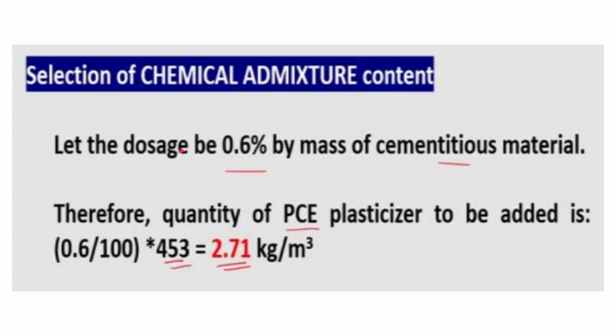Now selection of chemical admixture. Let us assume that the dosage of chemical admixture is 0.6% by mass of cementitious material. Because the cementitious content has been found to be 453, 0.6% will come to be about 2.71 kg per meter cube, which is the amount of PCE, polycarboxylate ether plasticizer to be used.